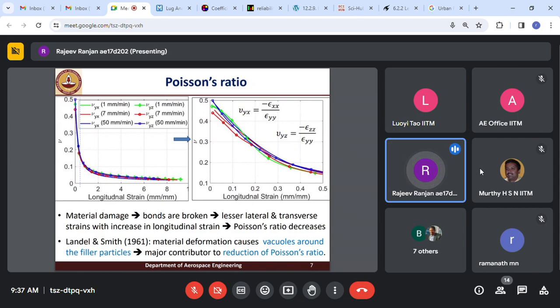Poisson ratio is also an essential mechanical property for structural integrity analysis, and it was determined during the uniaxial tensile test. Since there were two cameras, we calculated the Poisson ratio on both the lateral as well as the transverse surface, and it has been observed that the Poisson ratio variation was the same on both the surfaces as well as for all the displacement rates. It was close to each other.